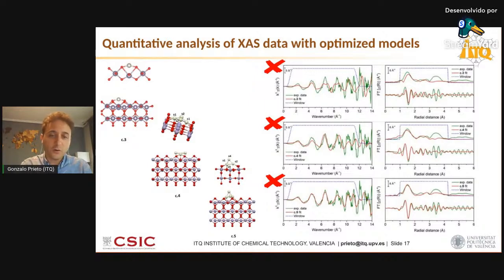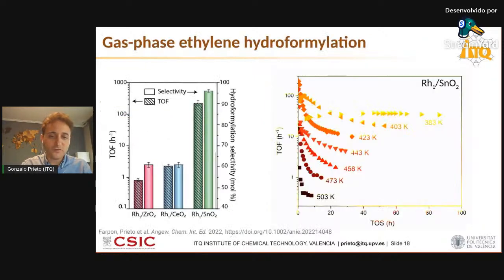So we did that to ensure that all these single atom catalysts I'm going to discuss here did show a monatomic rhodium dispersion on the different oxides. And then under industrially relevant conditions for ethylene hydroformylation catalysis, all these oxide-supported single atom catalysts showed activity. This is what I'm showing in the left-hand side plot, the bar plot. As you can see there, catalysts supported on zirconia and ceria showed modest activities, turnover frequencies, the dashed bars, and also modest selectivities, around 60% to hydroformylation.